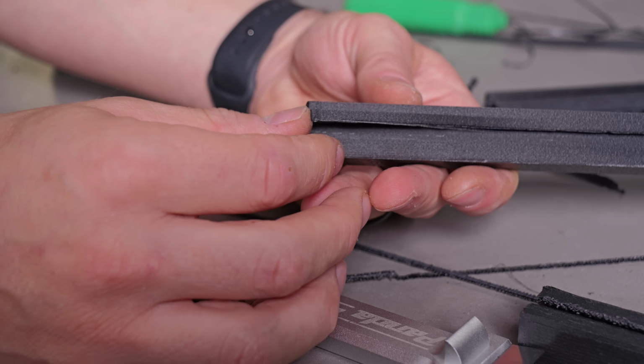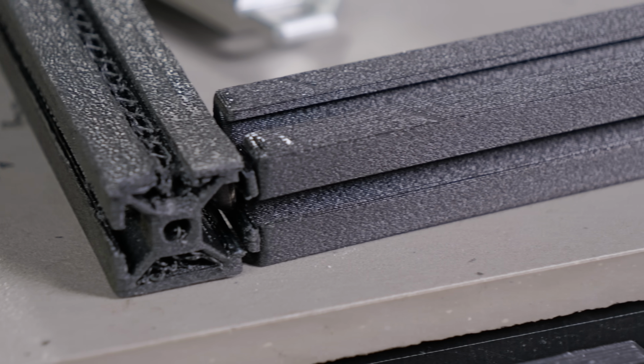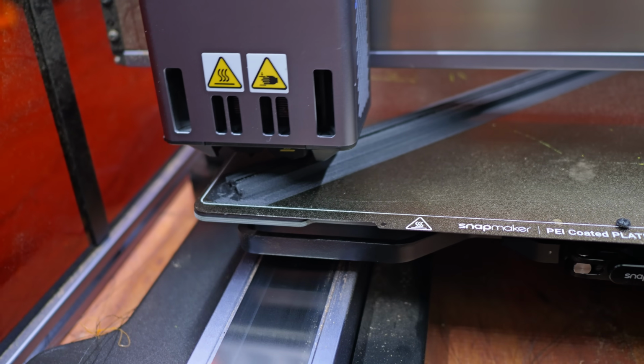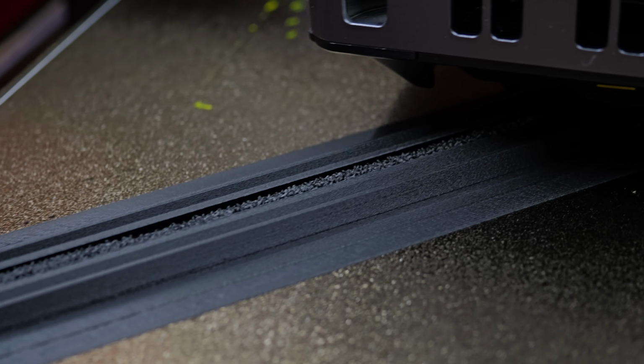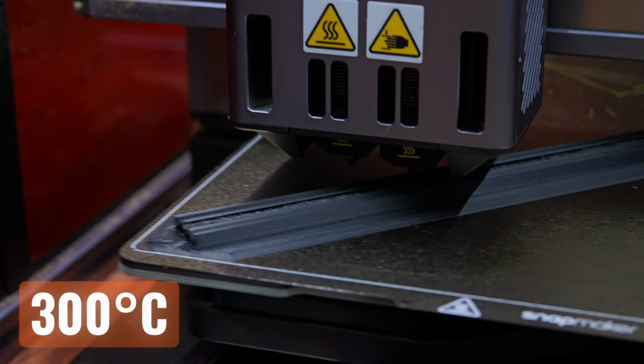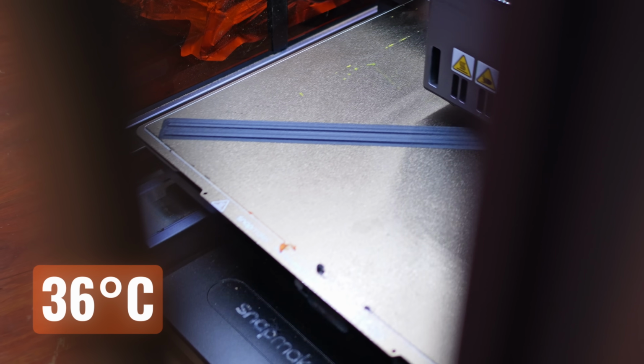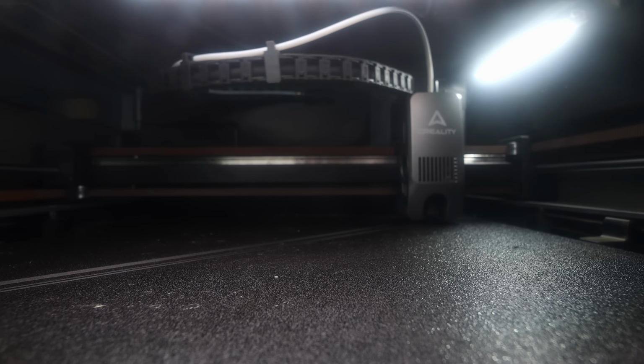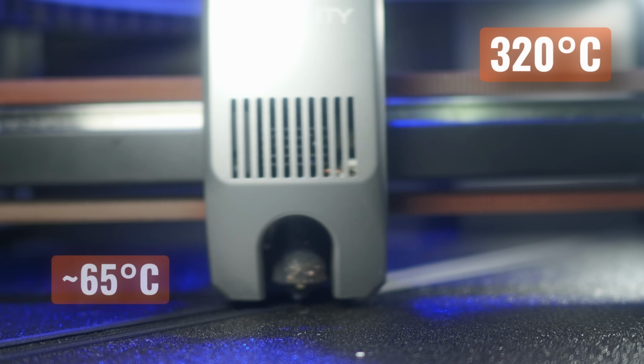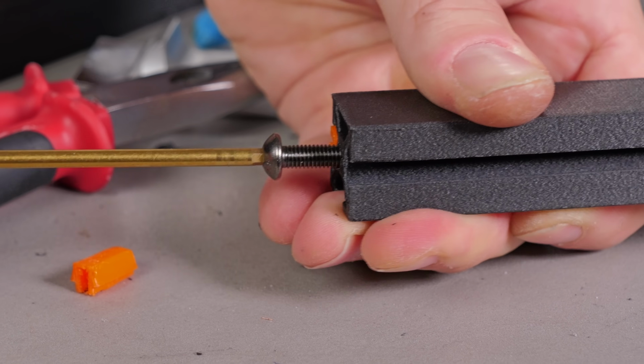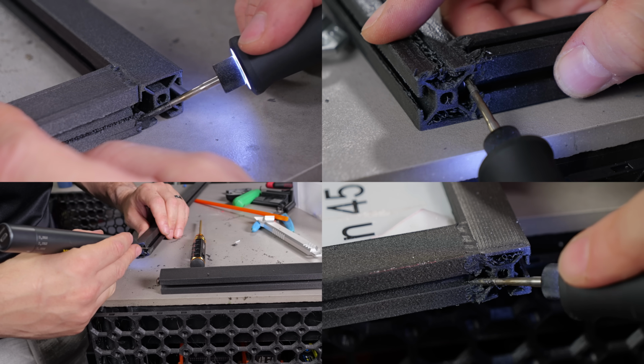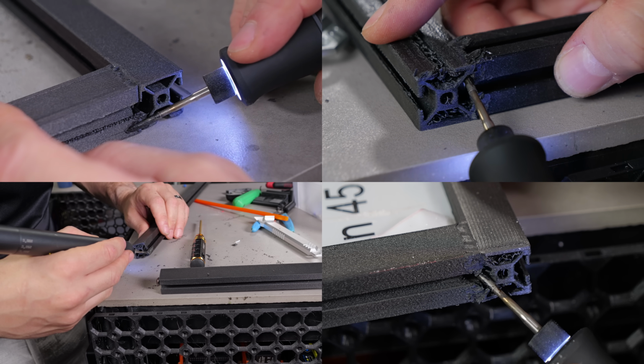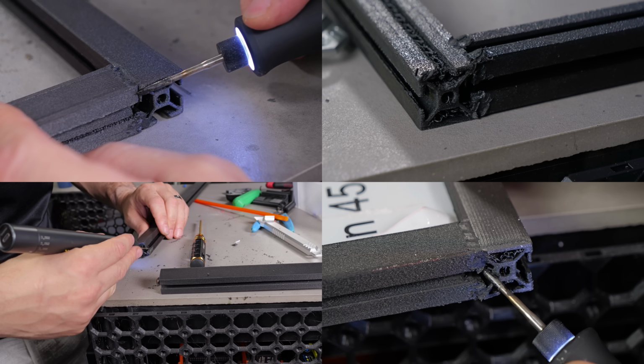First of all, during the assembly, the extrusions did break in a bunch of predictable places, though interestingly, only the ones that were printed on the Snapmaker, which I attribute to the relatively low 300°C max nozzle temperature, combined with the lack of a heated chamber. The ones printed on the K2 Plus at 320°C and a high internal chamber temperature were actually surprisingly robust. To get this project done, as you probably noticed, I ended up just welding the plastic together at all the different joints, which wasn't glamorous, but got it done.